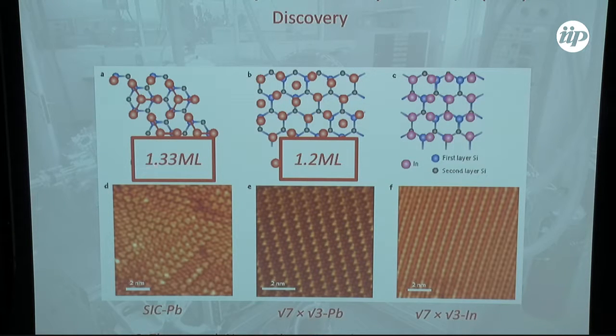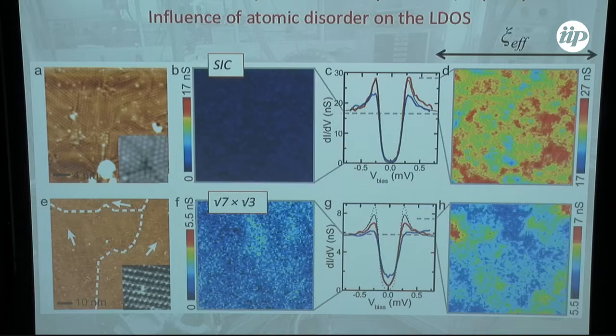And also there is another one which is called striped incommensurate lead. It's a different crystallographic structure, but also very dense, still denser. And in 2010, this group, a Chinese group, found a gap to appear in these two compounds below 2 Kelvin in this and below 1.6 Kelvin in that. And they claimed that it is superconducting, okay? And we wanted to check it.